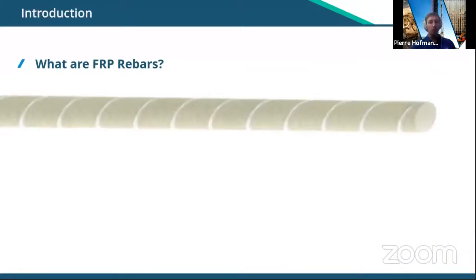The product we propose is a rebar following this geometry. We have two main features. One is the surface is sand coated. This is just to increase the roughness of the surface, so it will increase bonding with concrete. And the second feature is this helical wrap. So we see the spiral going along the bar. This will create surface deformation and create small ribs. The two features together will bring a great bonding property to GFRP.